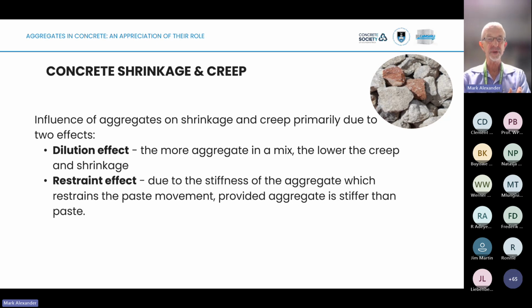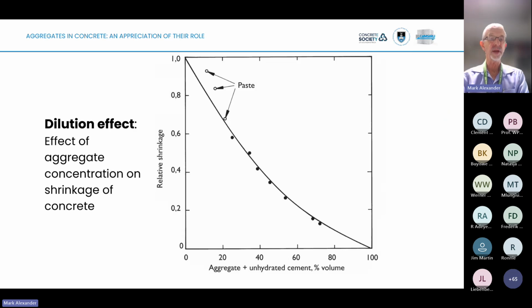If it's a stiffer aggregate, it tends to restrain the paste movement and tends to give higher elastic moduli, lower creep, lower shrinkage. And we've seen the one already here. This is the dilution effect. Coming down again, remember the concrete, these last 2 points on the bottom right. And you can see there that the concrete shrinkages, in this case, are less than 20% of the paste. And so that's the dilution effect, very important.